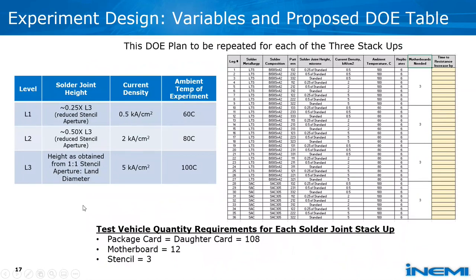This is the DOE, the design of experiment tables, and the various elements and their various variables and their levels. So it's a 3x3 DOE. The 3 variables are solder joint height, current density, and ambient temperature of experiment. These variables have been chosen after looking at the design of the test vehicle, as well as how long it would take for some electromigration effect to occur. The current density of 0.5 kiloamps per centimeter squared, 2 and 5, and temperature 60, 80, and 100.